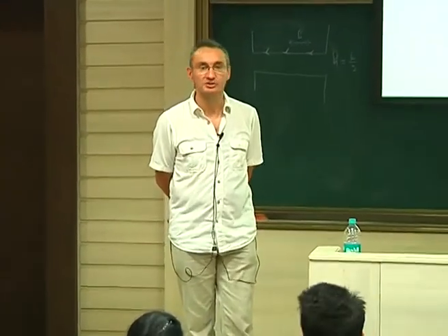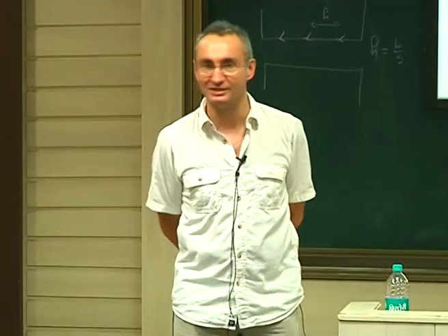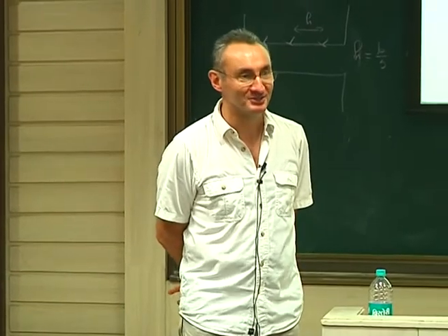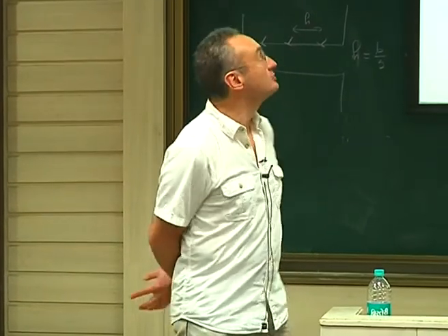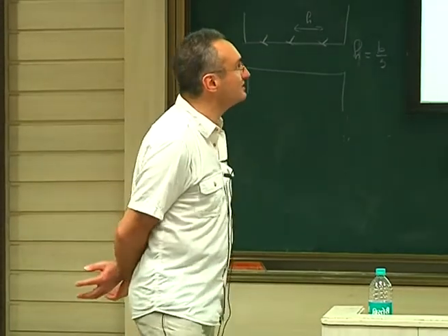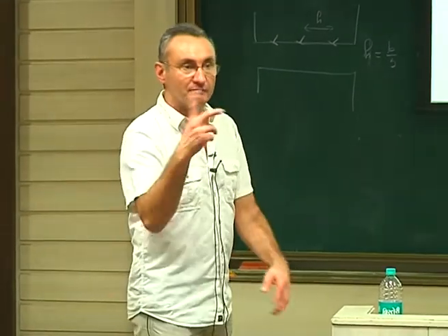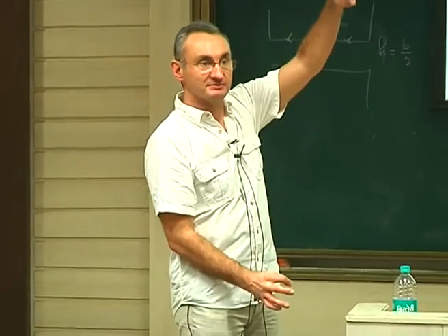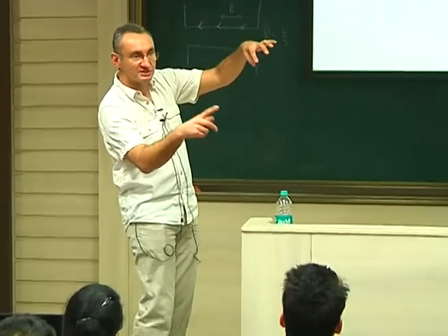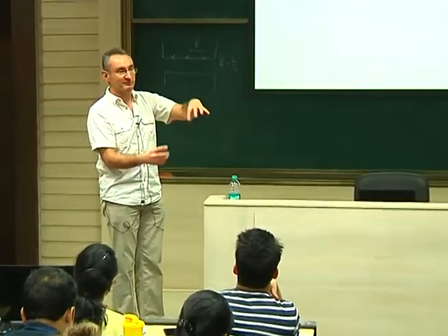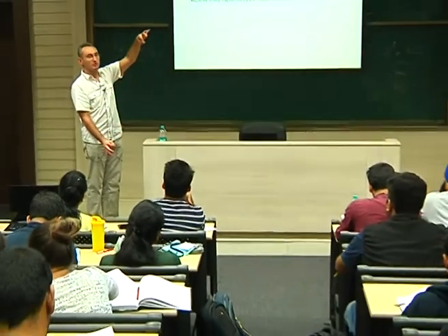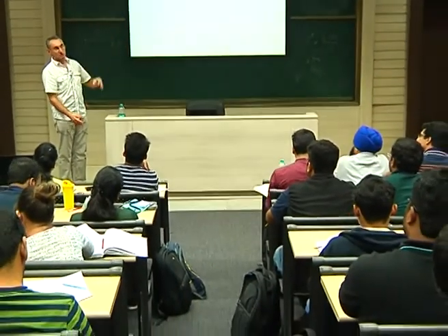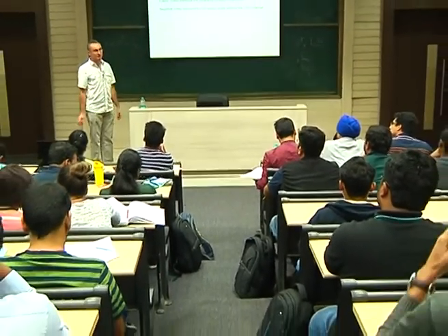No? Who is working on superalloys? I know that somebody told me. So you don't have any question? This one has no climb, yes, because this one has no climb. If I had put climb, then I would have these straight lines. Initially, I have this zigzag dislocation. If I add climb, then they will straighten into the 001 dislocation lines. So this is what I put as an ideal dislocation network.